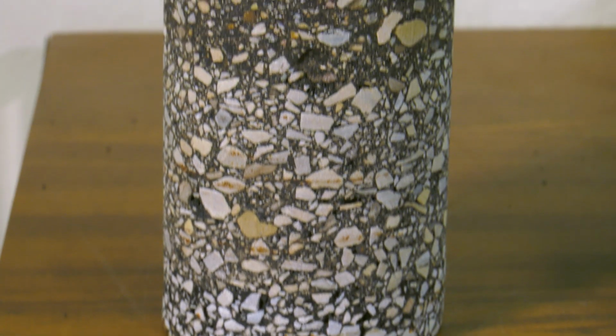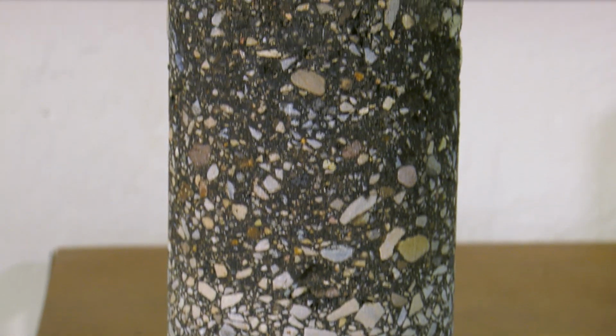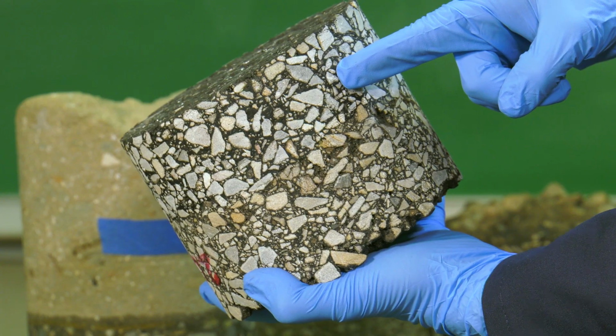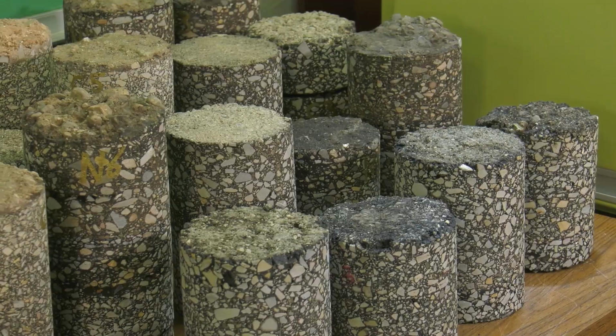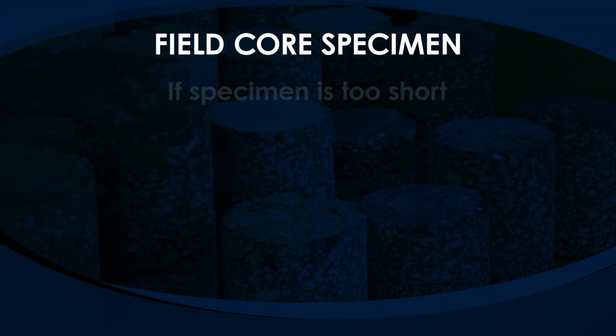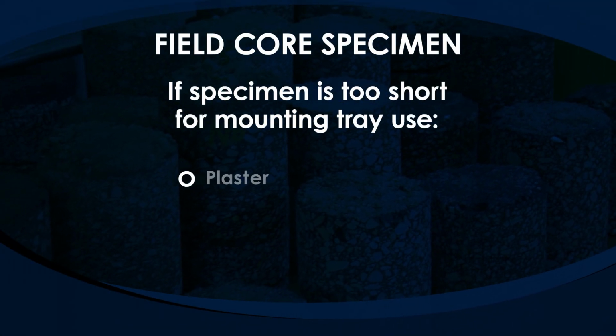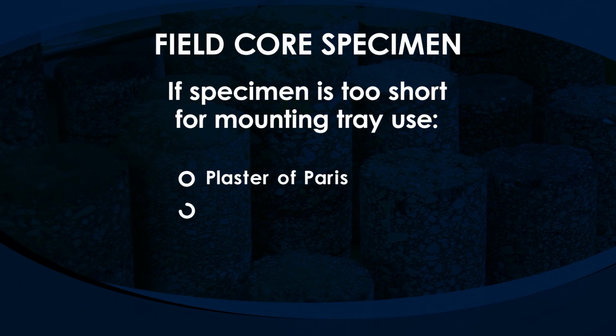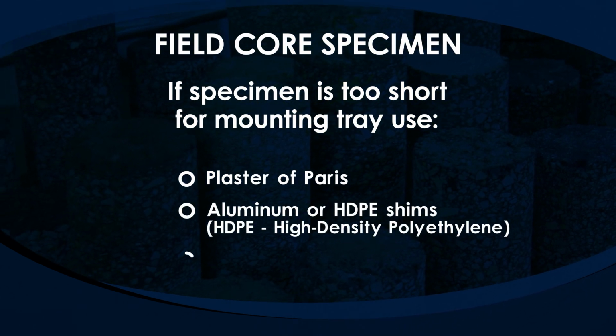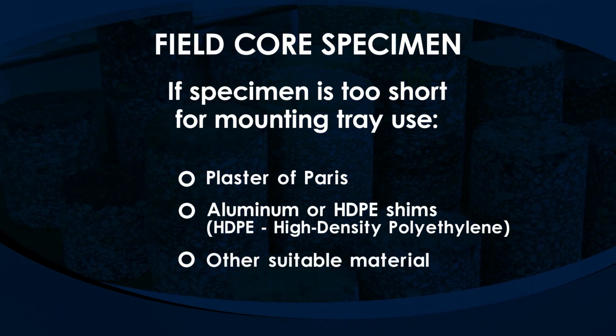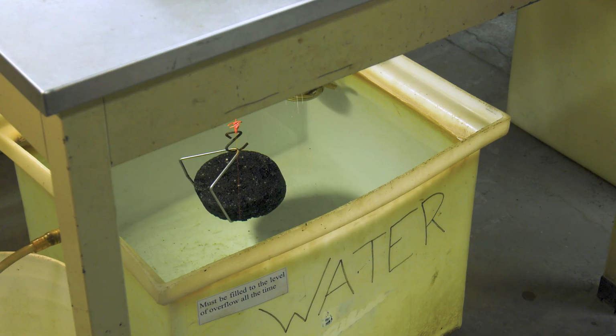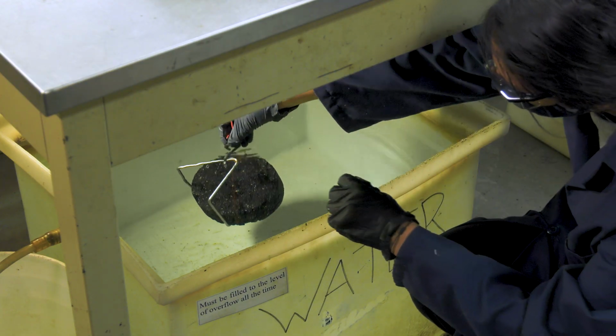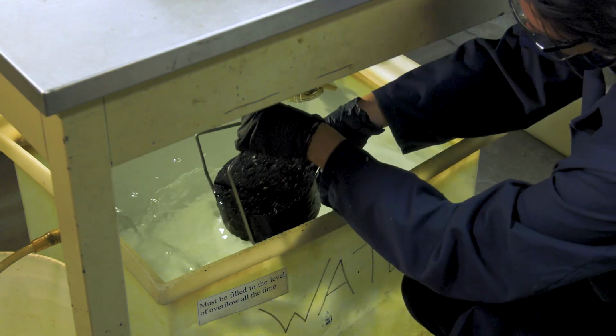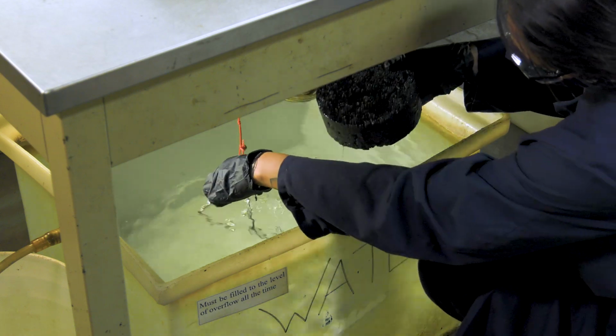Field cores are tested at the air void content and thickness at which they are obtained, or cut or trimmed to evaluate the layer of interest. If the field core specimen is too short for the mounting tray, plaster of Paris, aluminum or HDPE shims, or other suitable material can be used to fill the mounting tray. Determine the bulk specific gravity of the test specimens as suggested in AASHTO T166.